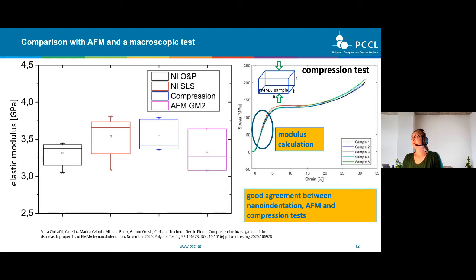And if we then compare those results, so in blue the compression test, the macroscopic test, to in black nanoindentation, the simple Oliver and Pharr method, or in red the nanoindentation with the modeling. And in pink, we have also AFM nanoindentation with the GM2 modeling. And what we can see here is that those measurements are in good agreement with each other. And there is also a publication about this topic from me and my colleagues from Montanuniversität Leoben, which you can see here at the bottom of the slide.